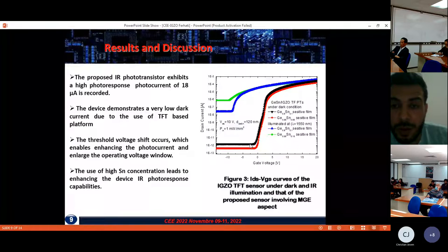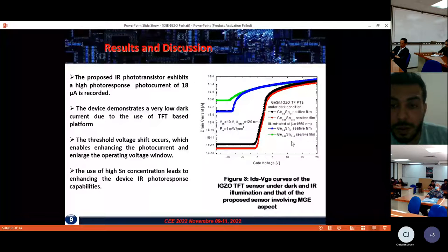It can be seen also from this figure that the use of a higher tin mole fraction can allow enhanced absorption capabilities of the device. It can be seen also that the threshold voltage shift under illumination occurs, which enables enhancing the photocurrent in a large operating voltage window.